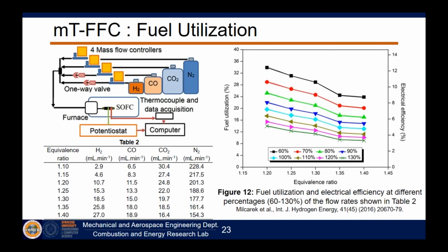And again, this is happening within a controlled environment. We have a furnace, so we're not actually heating our fuel cell in the flame. So this isn't perfect. We're also controlling the flow rate, but there's no chemistry limit here where we can't get beyond 100% fuel utilization. If we could, the project might have ended here and we would have been done. But we can see that it is possible to utilize the syngas at much higher utilizations than was initially believed in direct flame fuel cell research.